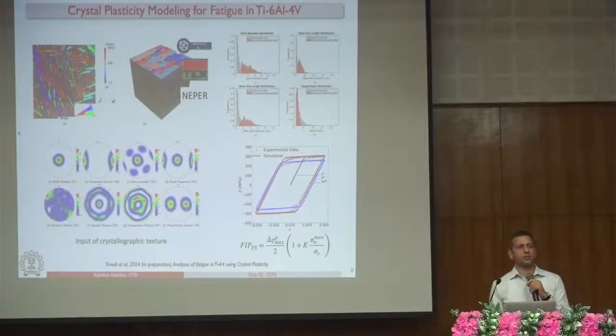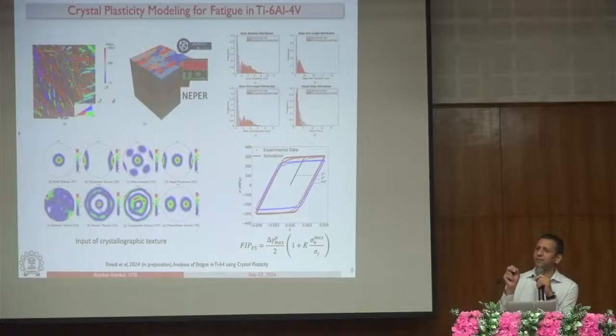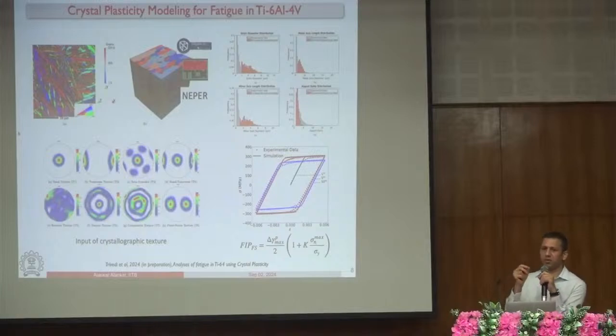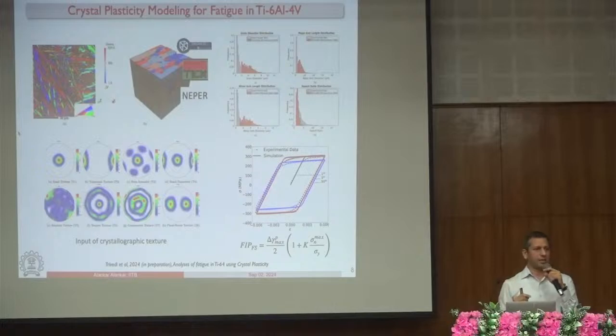So rather than running for 50,000 cycles, for example, where you see material failing in the lab, we can run it for only, let's say, 3 cycles, 5 cycles, maybe 10 cycles, right? Because there is a very well established theory that if the material is going to fail at 50,000 cycles, its signature should be seen much earlier. Remember when we started learning about metals, we were given a very simple test of how metals harden and fail. There was a very simple experiment given in all the textbooks that you take a wire and you bend the wire up, bend the wire down, and do it multiple times. After some time, the metal will become hardened at the bent location and it will break, right?